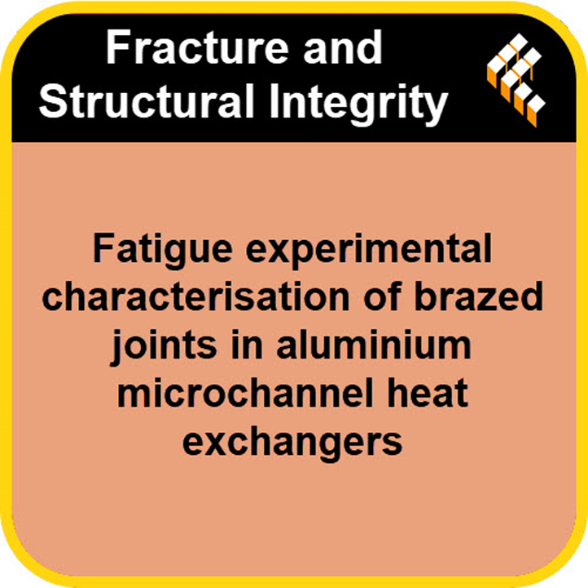What they found was that the thermal cycle had the completely opposite effect on the strength of these two base materials. Opposite. How so? It clearly showed that the way the material was made before brazing, rolled versus extruded, dictates how that alloy reacts to the heat treatment. Wait a second. You're saying the heat made one material stronger and the other one weaker. That feels counterintuitive. I always thought heating metal generally softens it. Well, that's often true, yes, but it really depends on the metal's starting condition, its history.